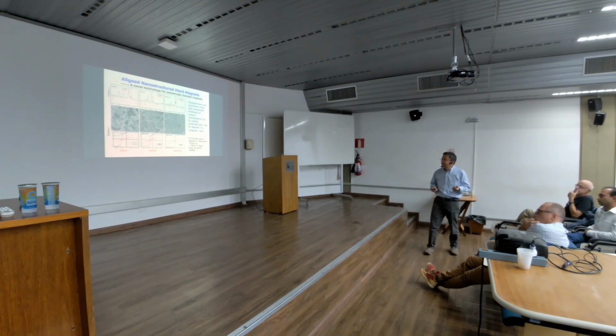And when talking about the good story of iron platinum nanoparticles, I did not tell you the dark side. The dark side is when you have those small nanoparticles with high coercivity, each of them is already a ferromagnet. They will stick together. Then you have no chance to separate them. Even with a 20 Tesla static magnetic field, we could not align them. But with these chips, we can easily align them, as you can see from the XRD and the magnetic measurement, highly anisotropic.